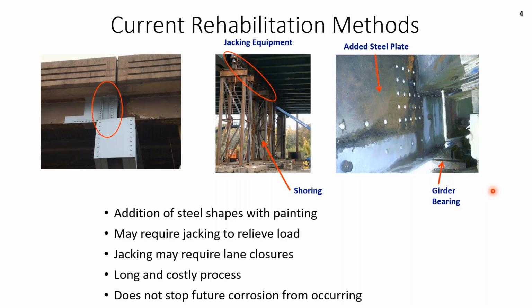And so the idea with this research was to try to come up with an innovative way to repair beam ends without jacking the structure, to come up with a repair that is structurally sound, but also, importantly, stops future corrosion. Because with this kind of repair, you can come in and do a steel repair, and in 10 years, you might be back repairing it again. We're trying to get a repair that's more long-lasting and durable.